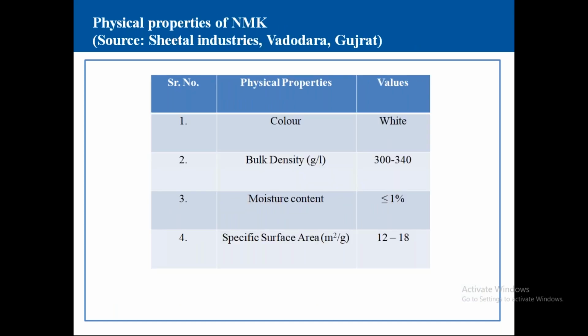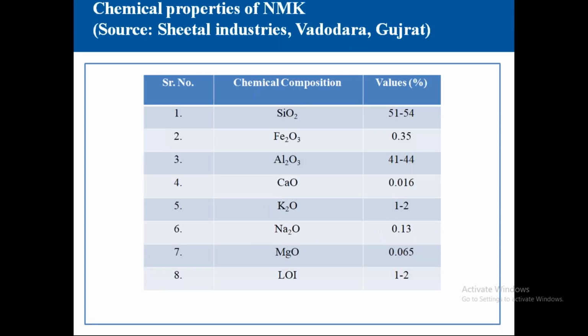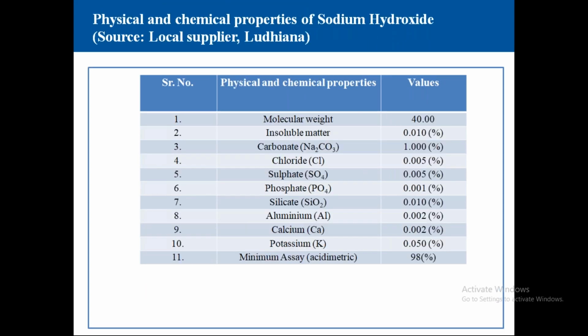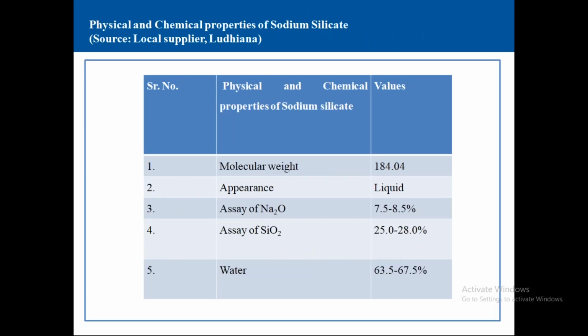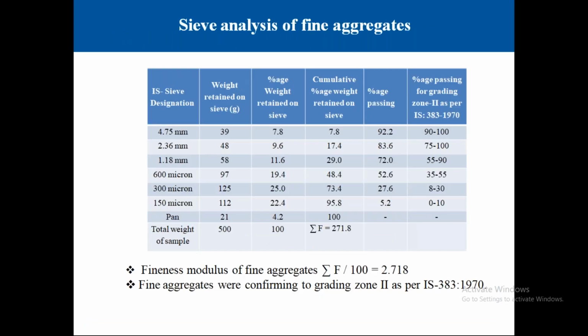These are the physical properties of nanometakaolin. Nanometakaolin color was white. Bulk density was given by the source from where we purchased, and specific surface area was 12 to 18. Similarly, the chemical properties: SiO2, Fe2O3, Al2O3 41 to 44, CaO 0.016, K2O 1 to 2, Na2O 0.13. Then the physical and chemical properties of sodium hydroxide and sodium silicate, these are the two activators which we have used, and then we did the fine aggregate sieve analysis.